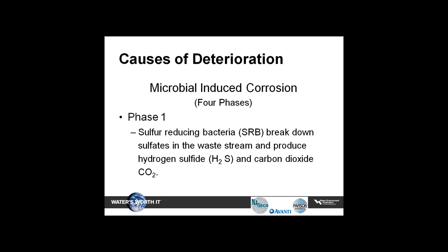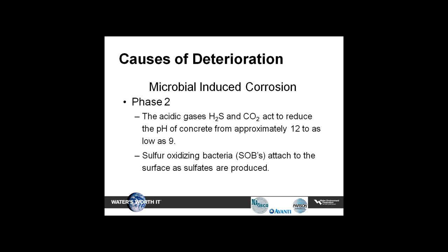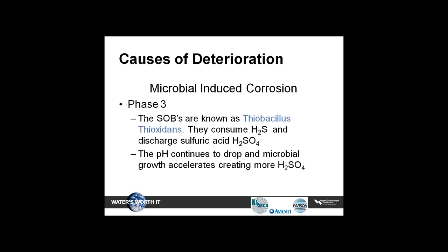There's generally 4 phases of MIC. Phase 1, sulfur-reducing bacteria break down sulfates in the waste stream and produce hydrogen sulfide as well as carbon dioxide. Not something that's visible. Neither one of the first 3 phases are visible. Phase 2 is where these acidic gases and carbon dioxide act to reduce the pH of concrete from approximately 12 to as low as 9. And these sulfur oxidizing bacteria attach to the surface as sulfates are produced.